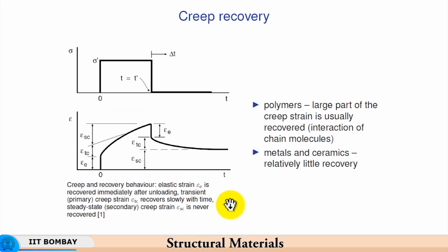Now, comparatively, the strain that is recovered here differs between polymers, metals and ceramics. In polymers, practically the entire creep strain can be recovered, because the mechanism of deformation is different. You have chain molecules which get extended during the creep process, and then they can contract as the stress is brought down, and you have a complete recovery of creep strain.